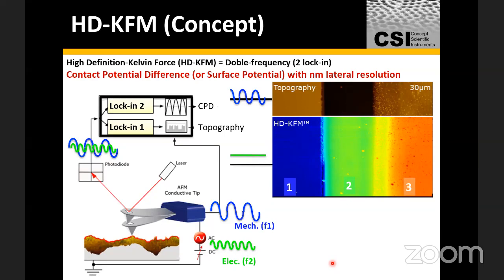One of the frequencies, typically the lower eigenmode, is used to infer the topography of the surface, which is really at the top here. You can see this is some sort of a device that has been, I guess, doped along these topographies. If you look at the bottom image, you can see the actual surface potential difference between region 1 of the surface and region 2 of the surface. The color coding really represents a difference in the contact potential or the work function of the material.